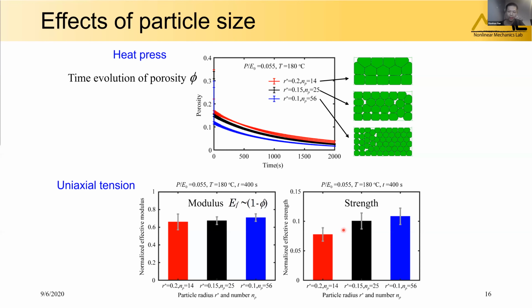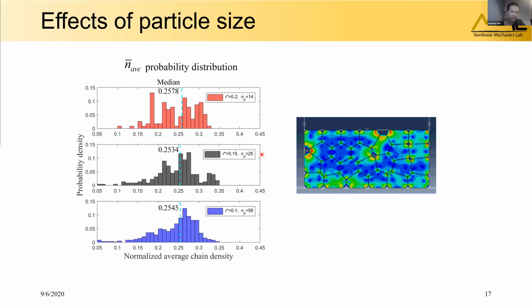However, the strengths show much difference among the 3 cases. To understand this, we plot the probability distribution of the interfacial chain densities. On the right-hand side is a snapshot of an example case. For each interface, an interfacial chain density can be calculated from the healing model. If we extract all the interfacial chain densities for all the interfaces, we can plot their probability distributions for the 3 size cases. And the results show that they show a similar median chain density. So the median degree of healing cannot explain the difference in the strength.